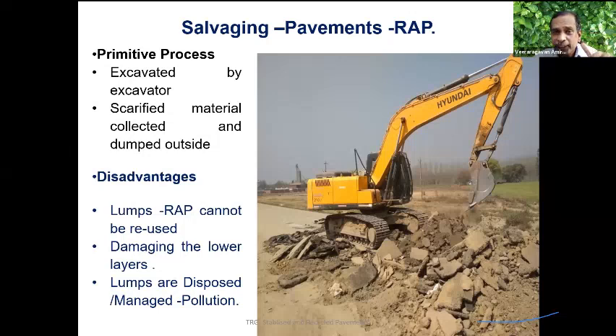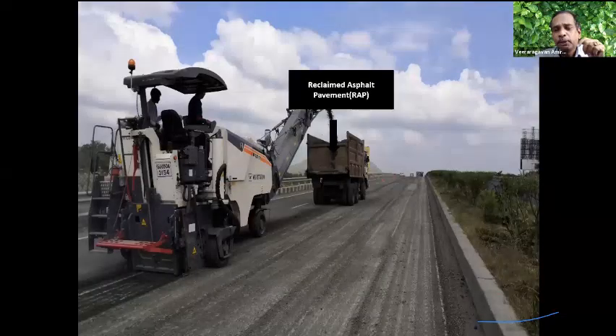But without damaging the lower layers, I have to mill. So the lumps are generally thrown away. These are black gold. Why throw them out? So you can mill the material. Now milling machines are available in India. You can mill any thickness that you need: 5 millimeter, 10 millimeter, 30 millimeter, 50 millimeter, 100 millimeter, it can be milled.